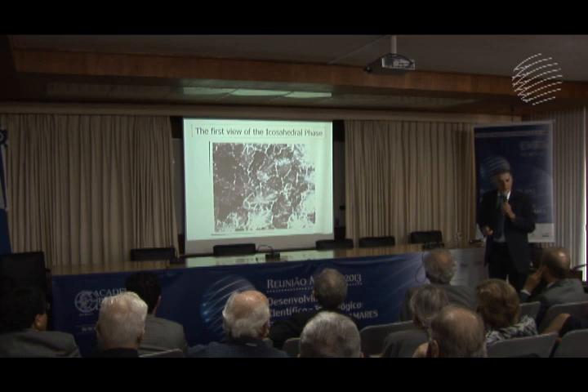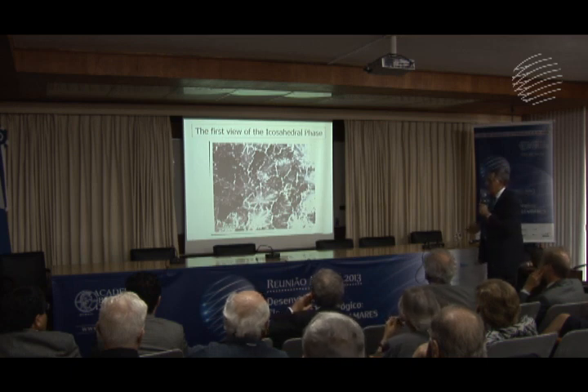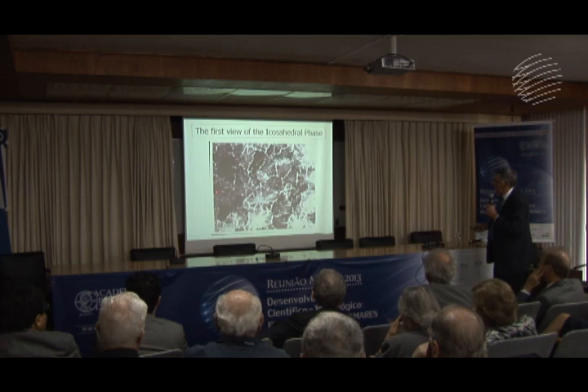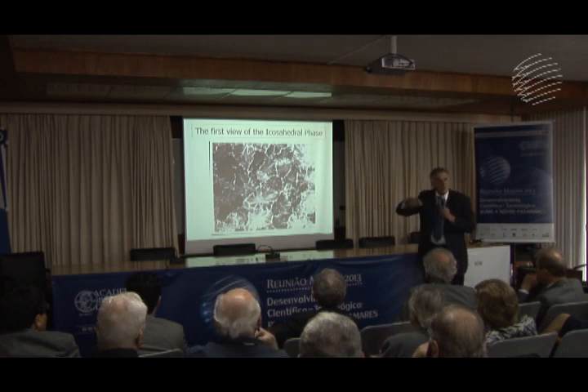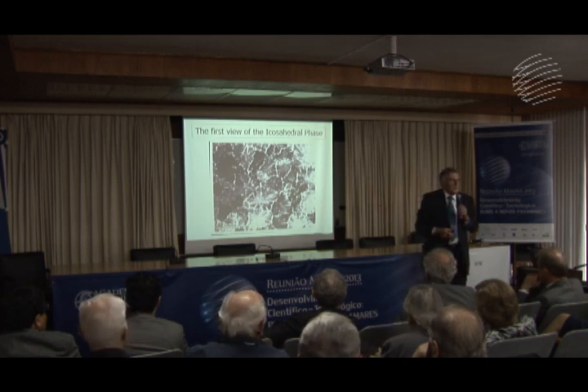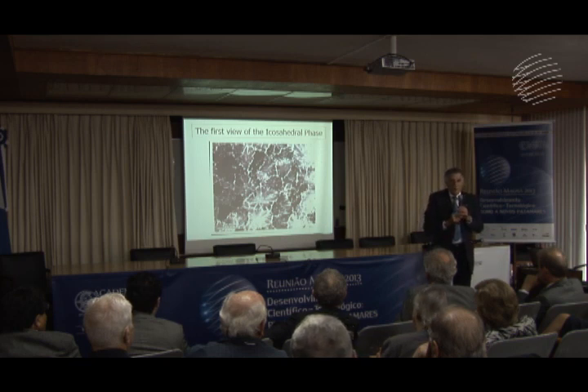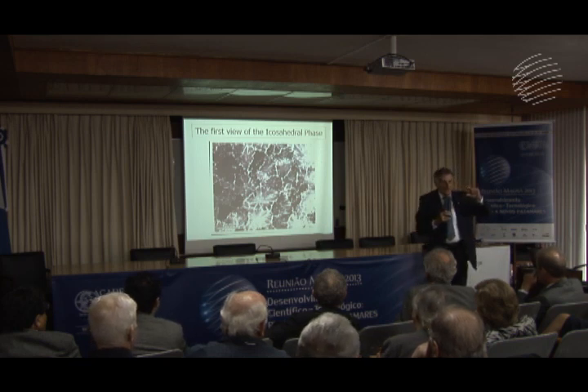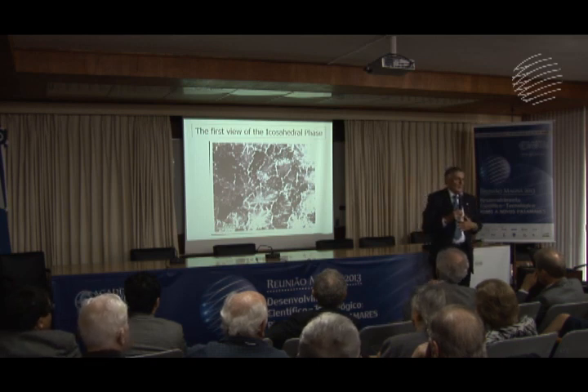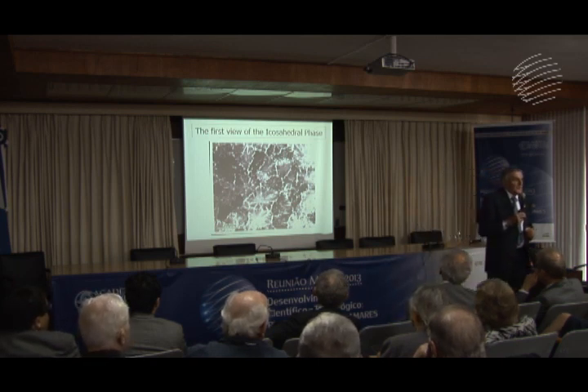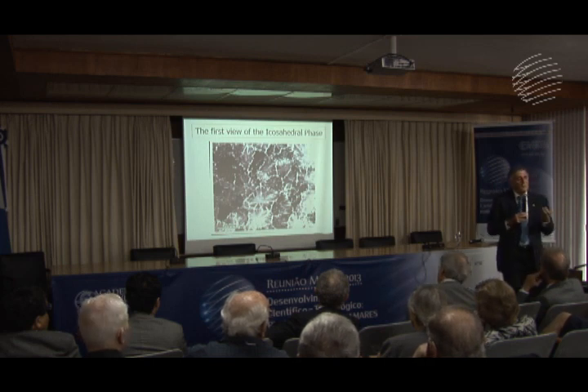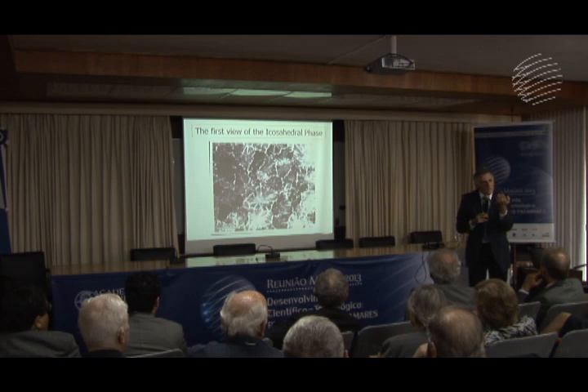But some of these crystals, and this is what was so interesting, some of the crystals are pitch black. This and this and this on the left. This is black. This is black. Now, this is a bright field image using that transmitted beam. If you see a picture like this, what it means is that either the specimen is very bad and thick and the electron beam doesn't go through, but don't think about me like that. I know how to prepare good specimens. So it's something else. And what it can be is that that crystal in this orientation diffracts heavily so that most of the energy goes through the diffraction, and the transmitted beam has almost no intensity. This is why it looks so black.